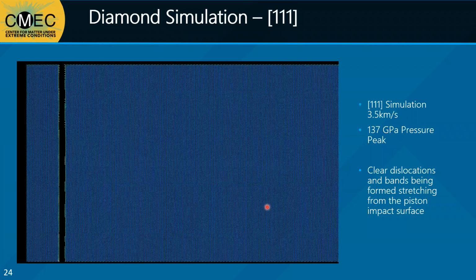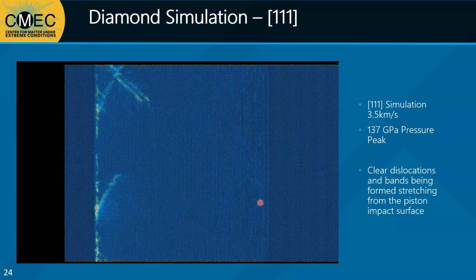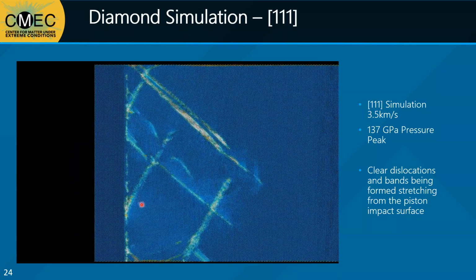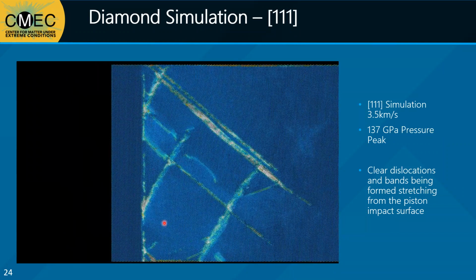Things get even more interesting when we tested shock compression along the 111 axis. Here we can see dislocations emanating from the planar impact surface, growing again at parallel and characteristic angles compared to each other. Many of these, because of the parallelism of these bands, we think are acting upon similar slip systems.